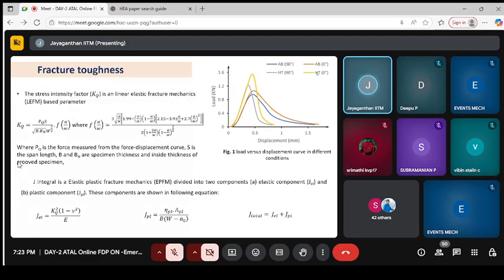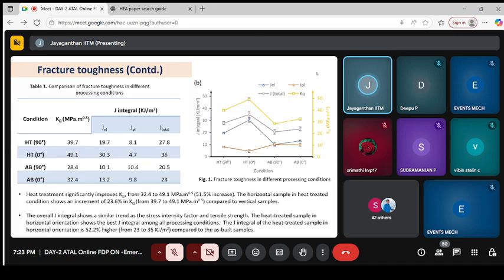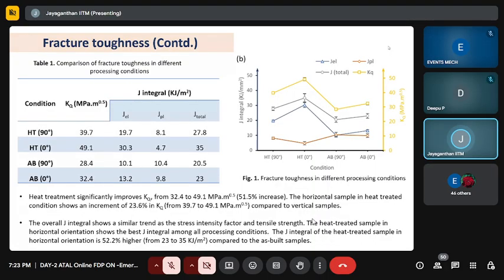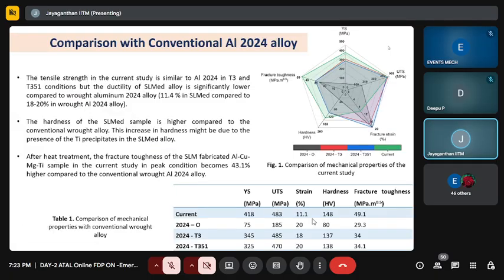And we did a 3-point bend test to study the fracture toughness of this particular 3D printed material. We are able to show that the heat-treated sample provides better properties. There we use the terms fracture toughness KQ and the J integral. The J integral takes care of how much plastic strain the material can take. That indirectly dictates the fracture toughness of the 3D printed sample as well as the post-processed sample. You can again see from this table that the heat-treated sample provides better fracture toughness.